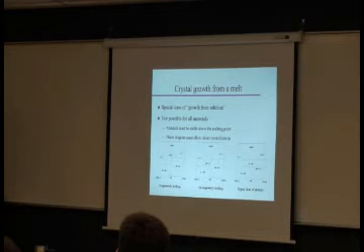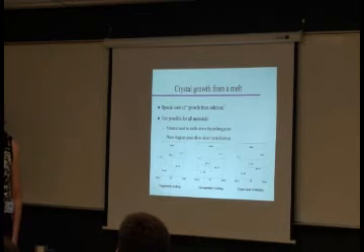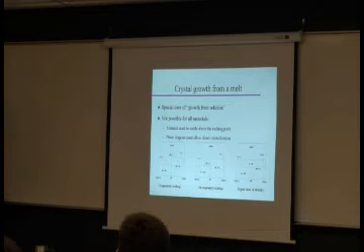And of course, this one is very bad too, because this one has an upper limit of stability. Compound AB is not stable above this temperature, but A and B are both solids above that temperature. There's no way you're going to grow crystals from a melt for that compound. This one, if you play some tricks, maybe you run lucky and you can kind of go back from here and form some of this. That one, don't even try. So if you are working with inorganic solids, it's probably worth looking up these phase diagrams if they exist.